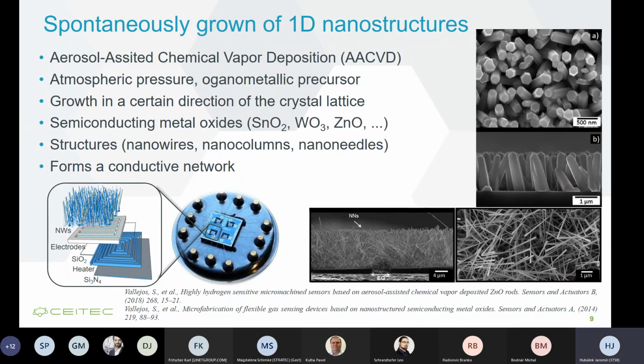Another approach is aerosol-assisted CVD at atmospheric pressure, and using organometallic precursors, we can create semiconducting metal oxides, for example, tungsten trioxide and zinc oxide, to grow nanowires or nanocolumns or nanoneedles. They grow spontaneously, creating a film in which each nanowire touches the others to form a conductive network. So finally, this film is well conductive and used for gas sensing.